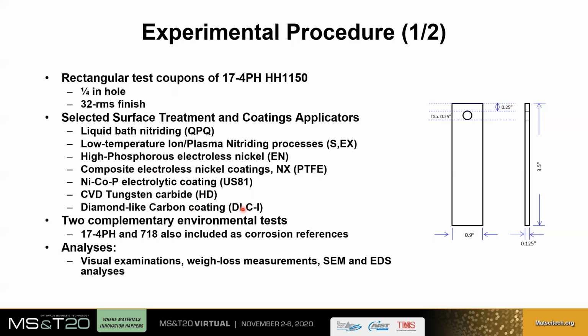So upon acquiring a great number of coupons with these surface treatments and coatings, we exposed them to 2 different environments, which I'm going to show in the next slide. And upon completing the testing, we run a number of examinations: visual, weight loss, SEM, EDS, and so on.